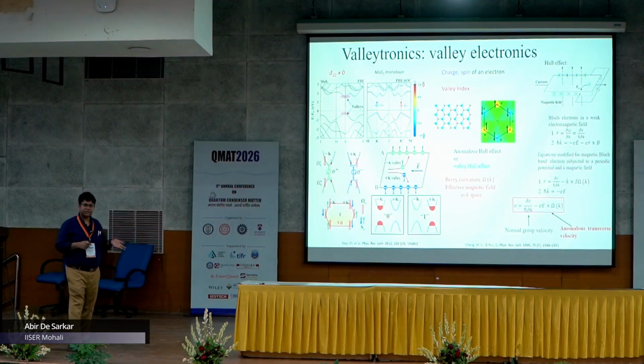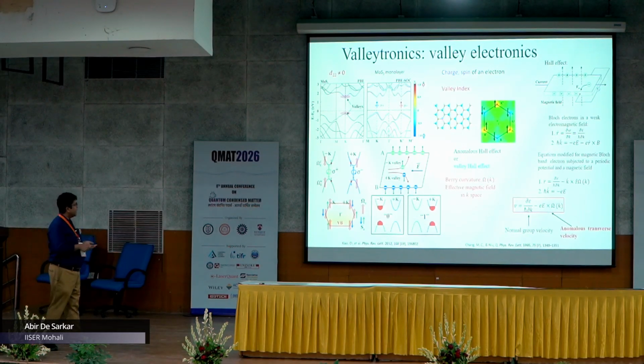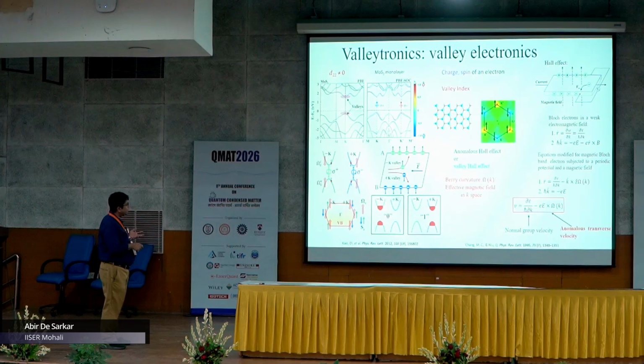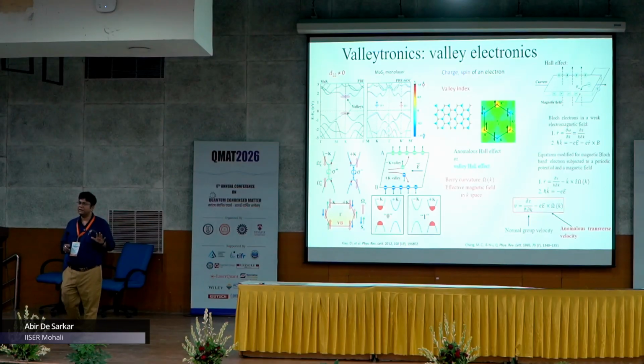And as you turn on the spin-orbit coupling, a Zeeman type spin splitting is found to occur at the K point in the band structure, and it gets a time reversed partner K prime or minus K. So, this is due to the breaking of the inversion symmetry. As the inversion symmetry is broken in the XY plane of this monolayer, the opposite spins are found to be locked to these momentum values K and K prime. K and K prime, or minus K, can play the role of zeros and ones in electronics, and they can be used to encode information.